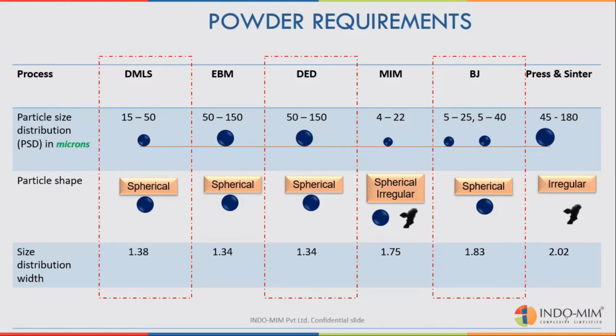Now, on the basis of powder characteristics, we widely classify all powder manufacturing techniques. You can see the particle size distribution and particle shape taken for this study. Very fine powder is needed for metal injection molding and the binder jet process. A moderate size, around 15 to 50 microns, is used for powder bed laser sintering. EBM and DED need some 50 to 150 microns. Anything beyond that can be used for the conventional pressing process. Almost all of the additive manufacturing techniques prefer a spherical powder.